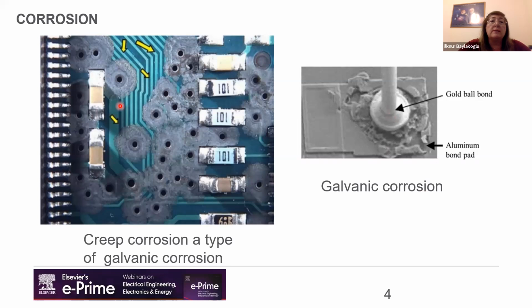Creep corrosion is also a galvanic corrosion, and it can form when silver or gold finished boards like this are exposed to a level of sulfur gas and moisture. At the silver and copper contact site, sulfur can dissolve into the moisture to form an acid electrolyte solution and promote the corrosion. Indeed, copper is much more reactive than silver. It serves as the anode and produces copper sulfides, which are subsequently precipitated and grow around the silver-copper contact sites,